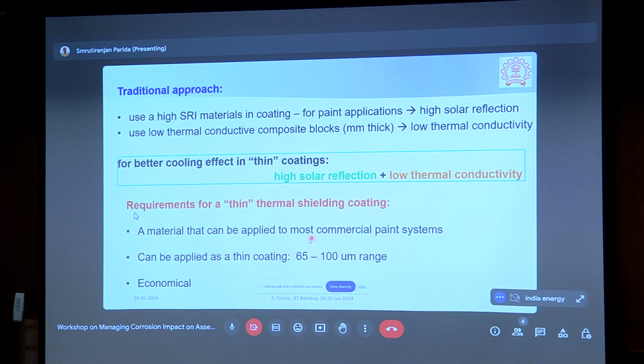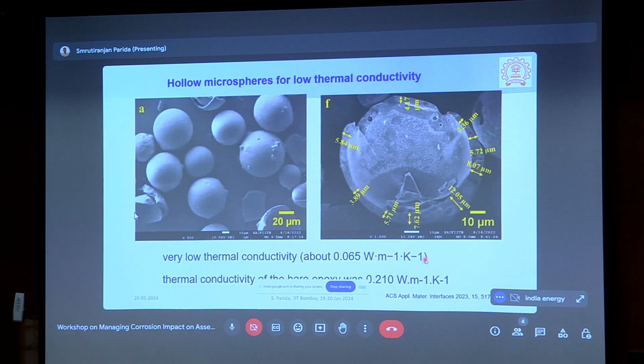The coating requirement is 65 to 100 micrometer, which is the range in which coatings are typically applied, and it must be cool. All the materials to be used must be very convenient. If we go through the literature, we find microspheres are the preferred additives added to paint. There are many types of microspheres people have worked with: glass microspheres, ceramic microspheres, and also cenospheres.